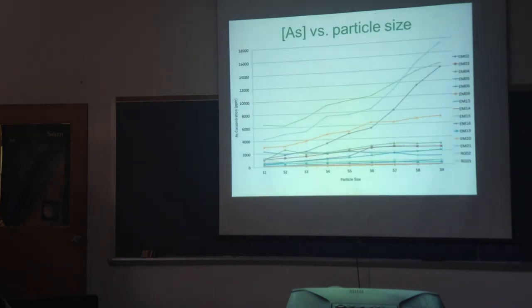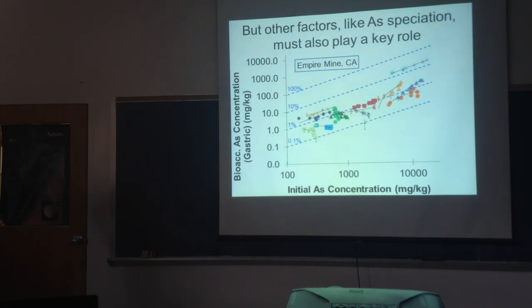So these are some plots that Chris made of just looking at arsenic concentration as a function of these 9 different particle sizes. And you can see that different samples kind of follow different categories, where some of them really are strongly higher in arsenic at finer grain. Some of them really don't have that much of a trajectory.